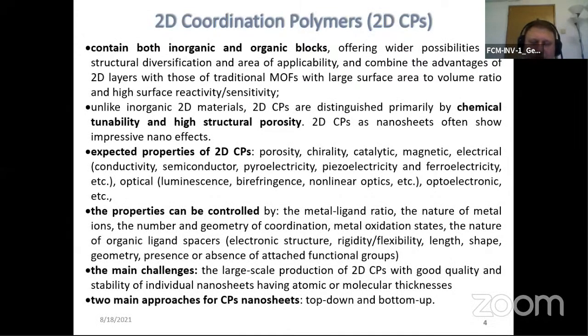The coordination polymers are distinguished primarily by their chemical tunability, high structural porosity, which give multiple nano-size effects. They have an array of properties that are of interest for multiple possible applications with large added value. And the properties of these materials can be controlled by multiple factors at the choice of the synthetic chemist, such as the ratio between the metal and the ligand, the nature of the metal ions that are used, the number and geometry of coordination, the state of metal oxidation, and the nature of the organic ligand spacers.